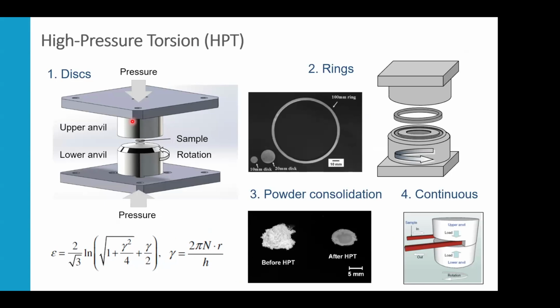As I said, we can produce any sample that's circular in shape, like a disc or a ring, and cylinders we will also be able to do, but we have to control the height to radius ratio, the height to diameter ratio, in order to get a more homogeneous grain distribution. But it's also possible to upscale the thickness of the sample. And usually the strain in high pressure torsion is associated with the shear strain in torsion. So usually N would be the number of turns, R would be the radius from the center, and H would be the sample thickness or the sample height.